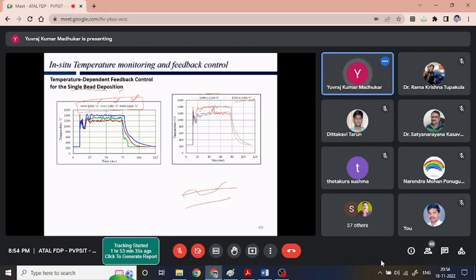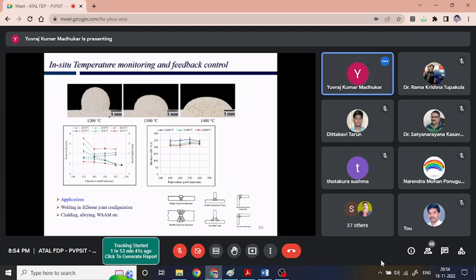Now the question comes, what advantage does this kind of control system give us? Here we could see, with respect to the different temperatures, let us suppose when you're working at 1200 degrees centigrade, the bead width is lesser and the bead height is more. When we're going for 1400 degrees centigrade, the bead width is more and the bead height is lesser. Of course, because at 1400 degrees centigrade we are giving more energy, the physical characteristics of the deposited bead change with respect to the set point temperature.